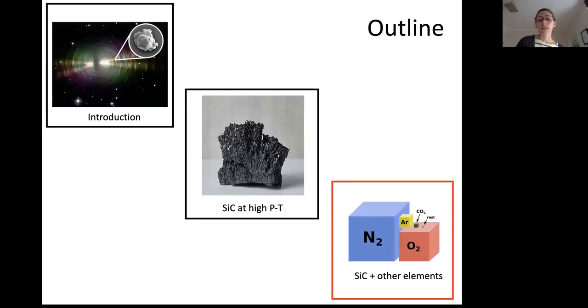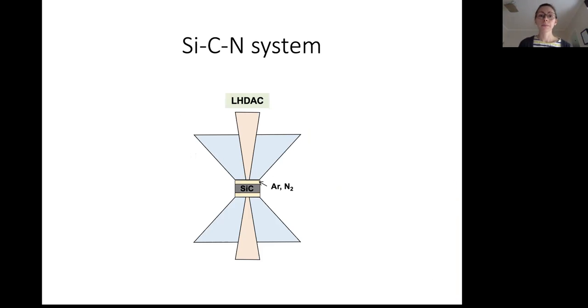Right, so continuing, the last study I'll talk about today is looking at nitrogen. Here's another schematic, and I have to say these experiments happened by accident at first. We were loading silicon carbide and wanting to use argon as the pressure medium. But in order to load argon, we would cool it down with liquid nitrogen. And in one of these experiments, some nitrogen made it into our sample by mistake. When we heated it up and saw these reactions, it took a very long time to figure out what was actually happening here.